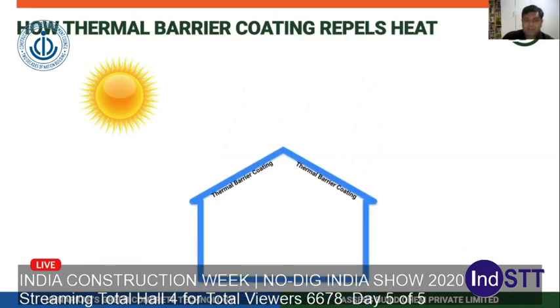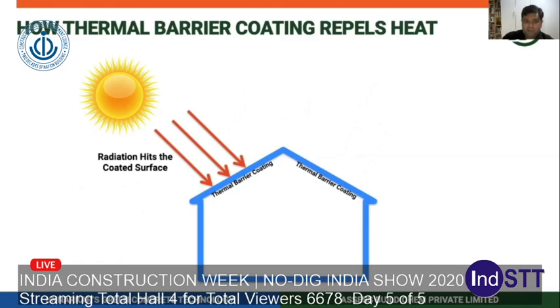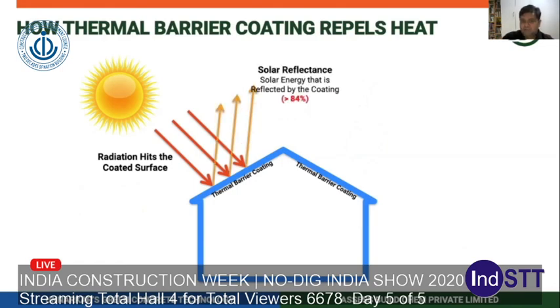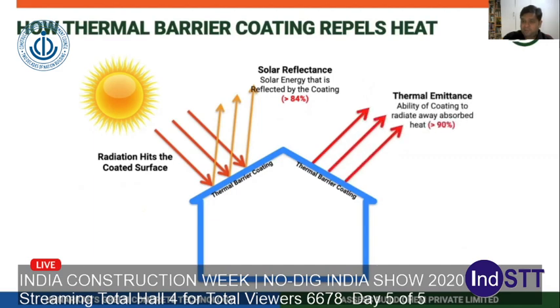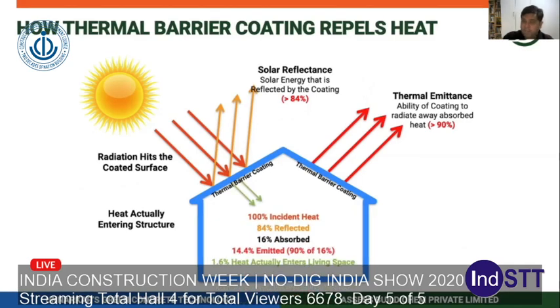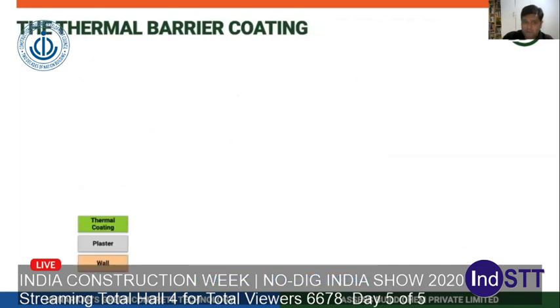This material works on the concept that it reflects the heat: most of the heat is reflected directly from the surface of the coating, and it also has a very high thermal emittance, which means whatever is the balance of the heat is kind of emitted away from your coating. So hardly about two to 2.5% of the heat actually enters your structure, and it remains much cooler in the long run.